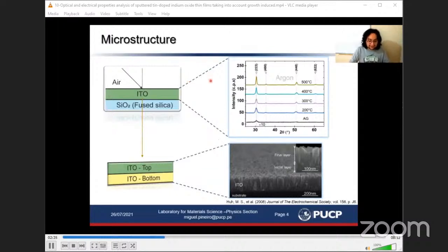First, we need to know how the microstructure of ITO behaves. This figure shows the XRD pattern of ITO thin films at different annealing temperatures in argon atmosphere, where we can see as-grown ITO presents an amorphous structure, and as we increase the annealing temperature, the film is more crystallized. So we know the first nanometers of thickness of the ITO film grow in a disordered way, while the following nanometers have a columnar growth as shown in this figure. Due to the complicated growth, we separate the ITO film into two layers. This figure is from this reference.